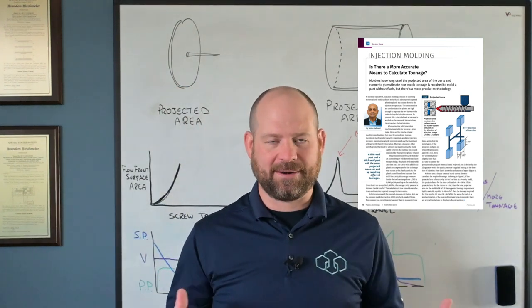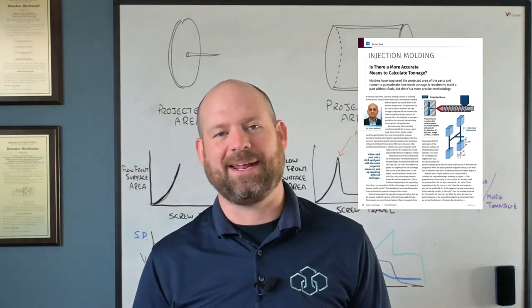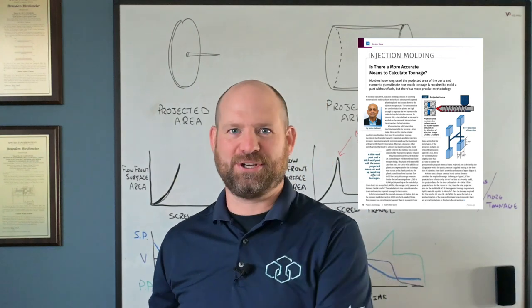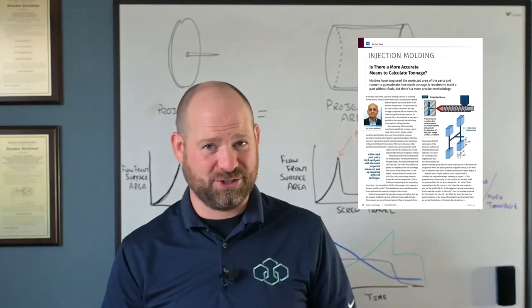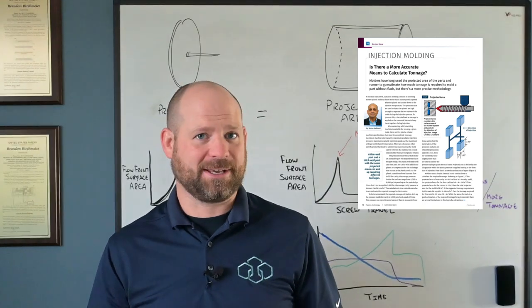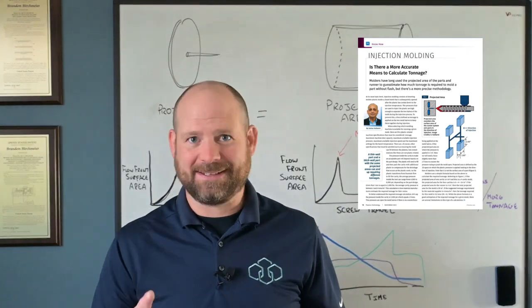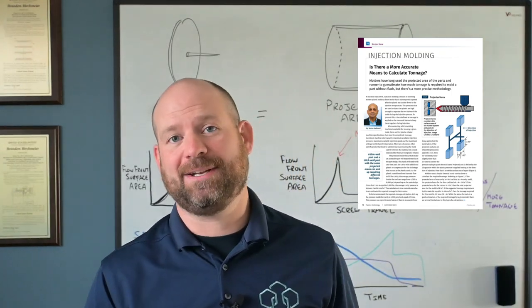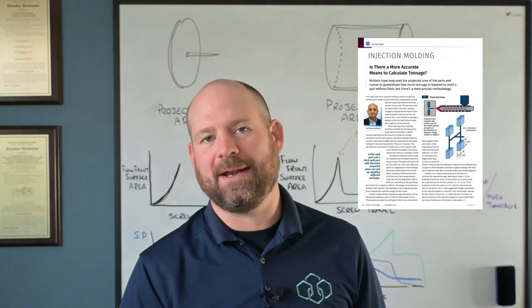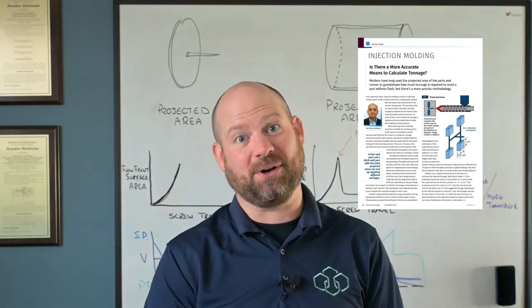He covers first the oversimplification that projected area has on tonnage determination. There's a lot more that can impact your tonnage requirement than just projected area alone. Think of things like flow length, gate location, obviously part design, and ultimately the pressure needed to fill your part out and how that impacts the tonnage needed to keep your parting line closed.